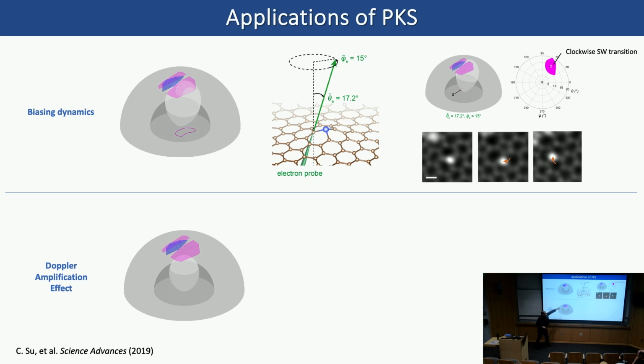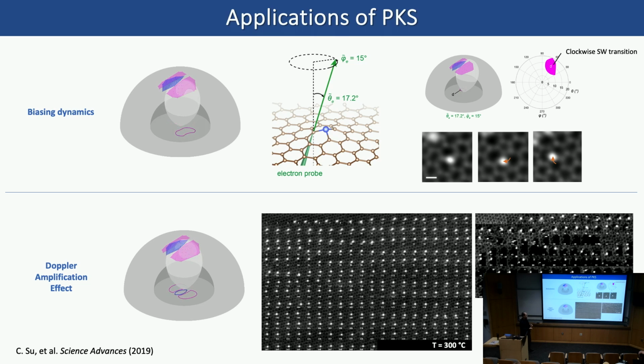Okay, so the shrinking and expanding ovoid actually depicts the real scenario when there is a lattice vibration. And it intersects with the color blocks from time to time. And when you have a more dramatic temperature change, then it will intersect with more color blocks. So the displacement cross-section, or the atom dynamic cross-section, will become bigger. So this is what we are seeing from our experiment.